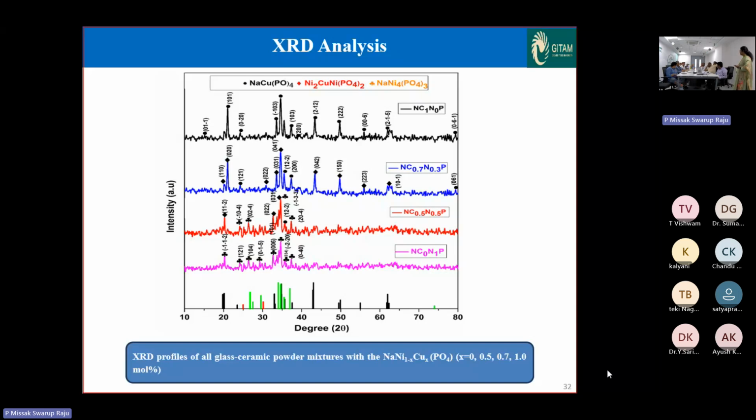now, since there are different crystals, like one is the NaCuPO4 phase, another is a second one, a third one, if you take an average, can you really apply the Williamson-Hall plot here? I don't think so, because different phases have different crystallite sizes. What you are really trying to do is merge 3 equations together instead of keeping them separate. If you go to your 14th slide,